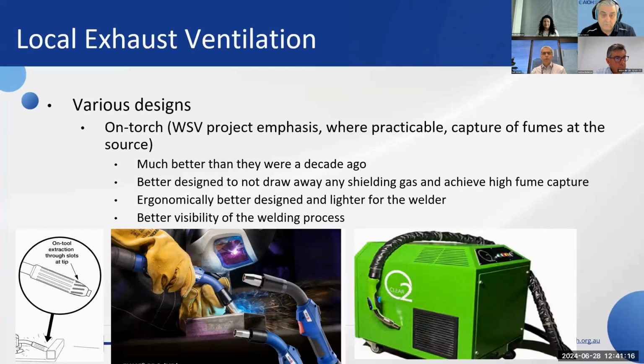And as good as powered air purifying respirators are, you need to consider controlling it as best you can at the source. So the workplaces that we're going to, some of the workplaces are talking about the on-torch guns aren't that great. I tried them out 10 or 20 years ago, and they are much better than what they were. So they're better designed. The problem with drawing away the shielding gas isn't what it was before. The capture can be effectively established to effectively capture the fumes without disturbing the weld itself. And they're much better in terms of being ergonomically designed, and in terms of being able to actually see the weld when you're undertaking the task.